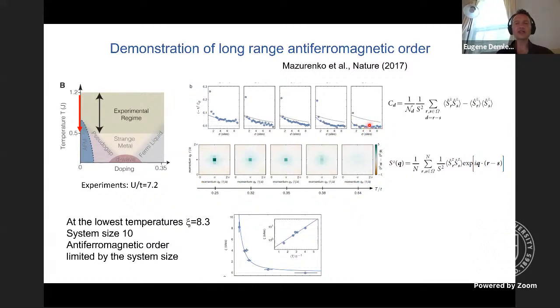And on the right, you see high temperature data, right? These are already spin correlations, just the usual two-site spin correlations, but the alternating sign has been taken out so that it doesn't oscillate. You see that we have weak correlations at high temperature, but as temperature is lowered, the correlation functions get stronger and stronger, and they become longer and longer range. So here you can see how the correlation function diverges at 0 temperature, exactly as we expect for a two-dimensional Heisenberg model.